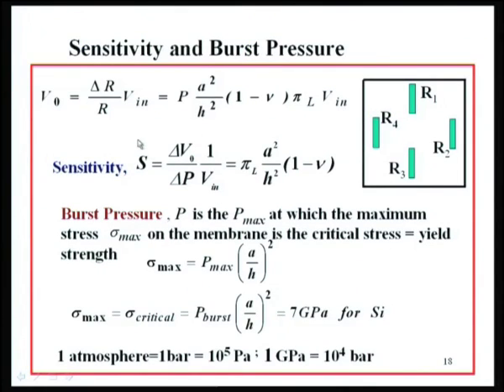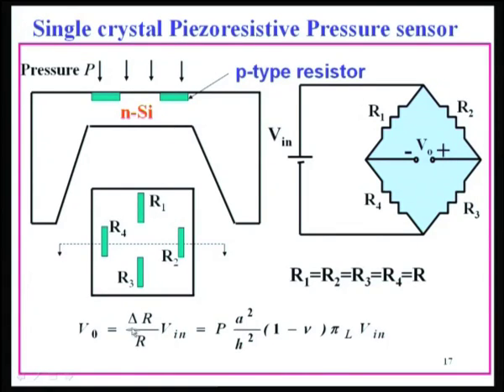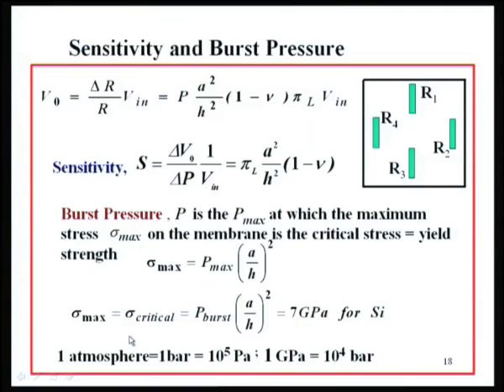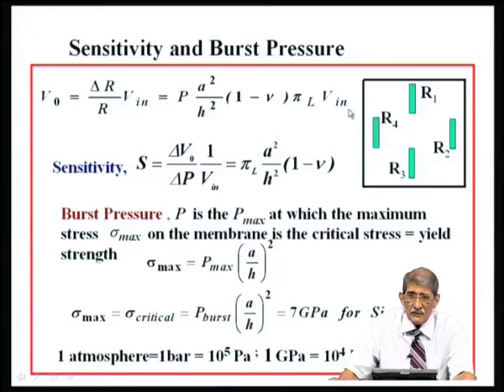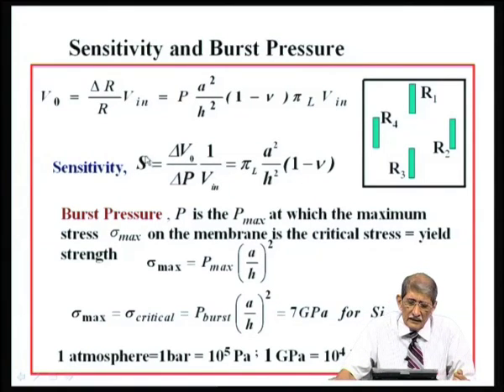Let us take a look at the sensitivity and the burst pressure. What is sensitivity? Sensitivity is V naught divided by the pressure. Okay. V naught is delta r by r into V in, which is P into stress, this quantity, into input. Now, in this term you see the pressure P. So, sensitivity is delta V naught divided by delta P. Delta V naught depends upon delta P, and of course, for a given voltage you divide by that. So, this is the quantity, that is pi L into A square by H square into 1 minus nu, straight away that will give you. So, to tell you in other terms, sensitivity will depend upon the material that you have chosen, longitudinal piezoresistive coefficient, and A by H ratio.